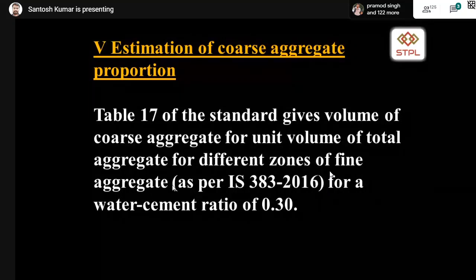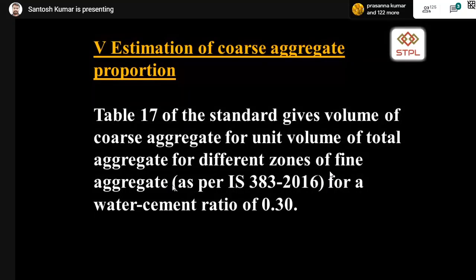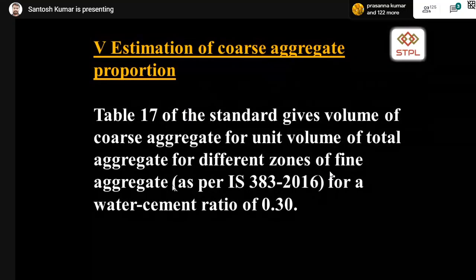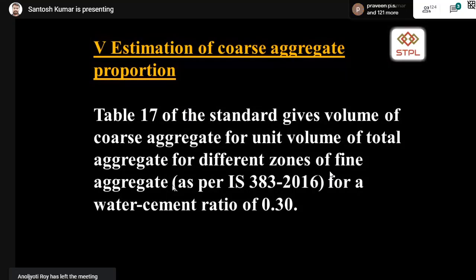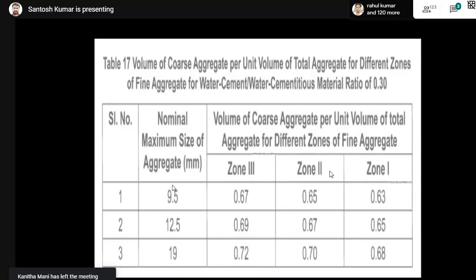Estimation of coarse aggregate. This is estimated from Table 17 of IS 383, and this is given for a water cement ratio of 0.30 based on the zone of sand. Day before yesterday, we discussed what a zone of sand is. If your sand is conforming to zone 2, and if you are using 19 mm coarse aggregate, the volume of coarse aggregate shall be 0.70. This is how it is adopted.